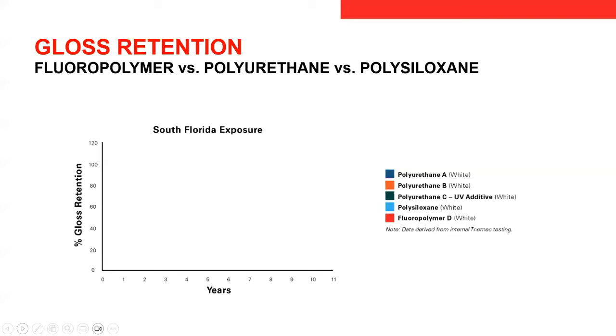Okay, let's start digging into some of the data here. Jennifer just talked about South Florida exposure. Again, this is widely used by the coatings industry, and the real downfall and limitation of it is that to get 5 years of data, it takes 5 years, or 10 years, it takes 10 years. As performance of coatings has increased over the years, what may have been a 2 year test has really grown into 5, 6, 7, 8, even 10 to 15 years. It just takes a long time to get that data in. So it's still widely used and widely relied upon, but it takes time.